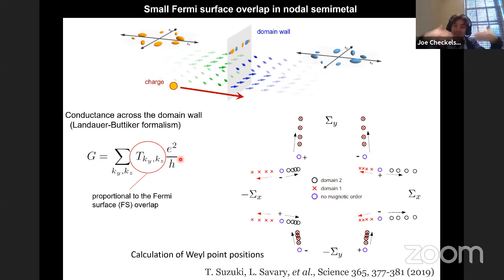And so then what you can finally couple to think about the Weyl points in the system is this was a beautiful part of a calculation done by the co-authors of this paper, where they showed that, for example, without thinking about the magnetic order, the Weyl nodes would be in one position. But then upon having one domain or the other, the Weyl nodes move in K-space, right? And it was the ability basically to tune the position of the K-space Weyl nodes that you could tune the overlap between them, right? And it seemed to be that could be what was responsible for this big response.